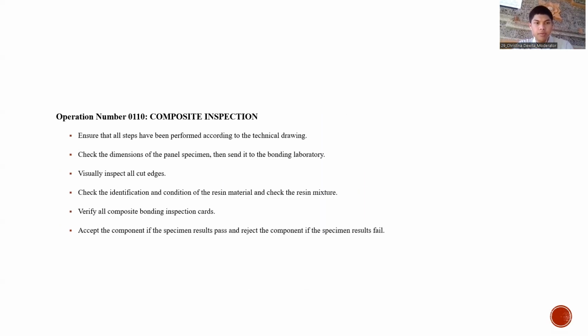And then the operation number 0110 is composite inspection, where we ensure that all steps have been performed according to the technical drawing, and then we check the dimension of the panel specimen, then send it to the bonding laboratory. Then visually inspect all the cut edges and check the identification and condition of the resin materials and check the resin mixture. And then verify all composite bonding inspection cards. Thus, we accept the component if the specimen results pass and reject the component if the specimen results fail.